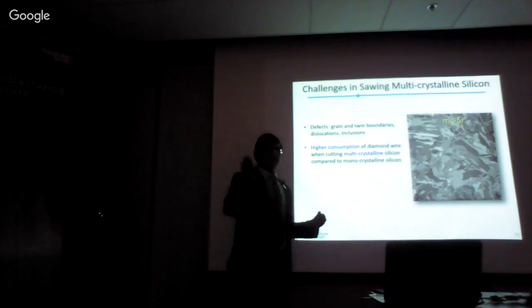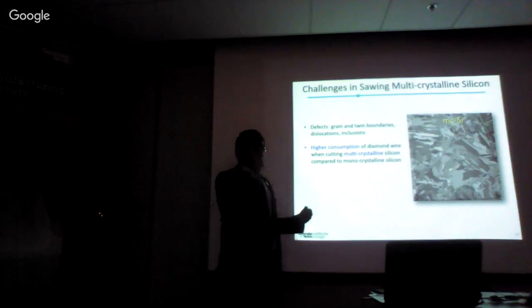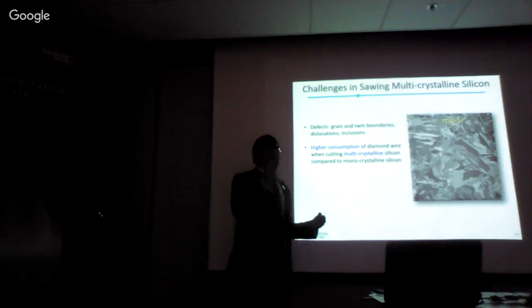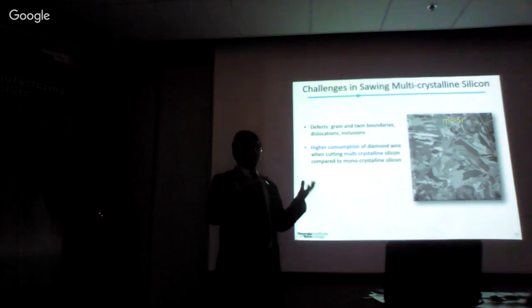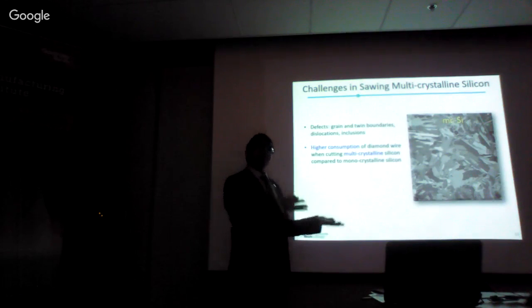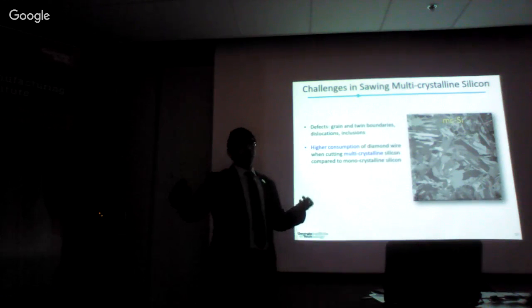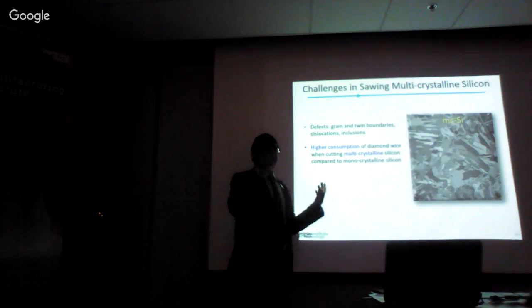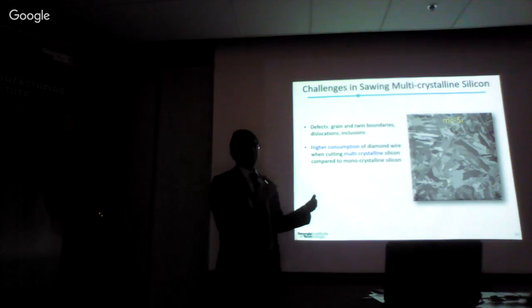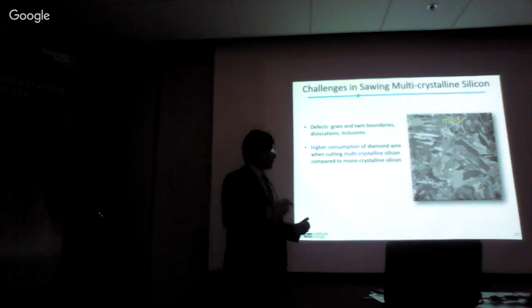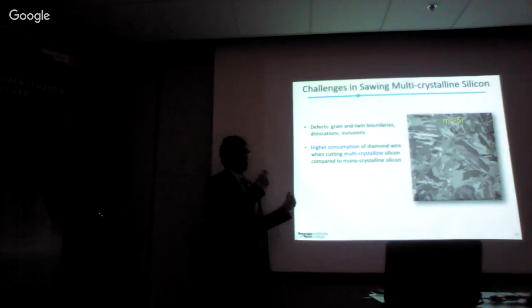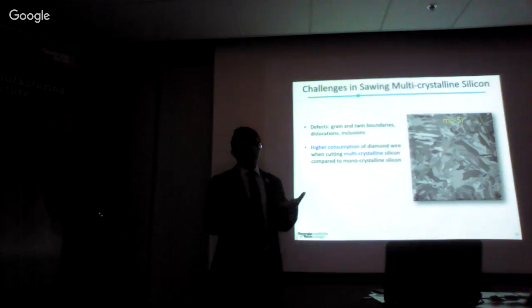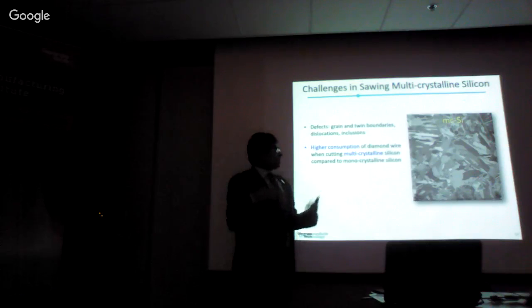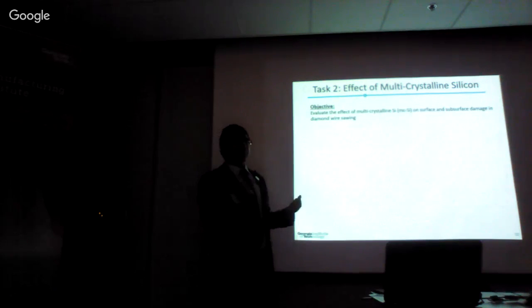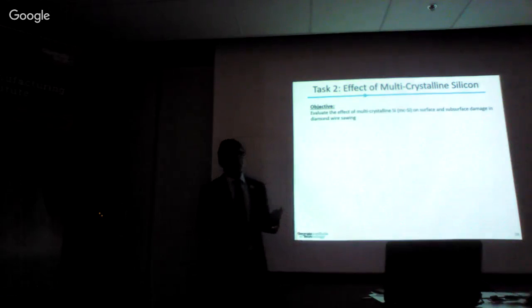boundaries, apart from silicon carbide, nitride inclusions, and dislocations, which affect the cutting of multicrystalline silicon wafers, leading to lower fracture strength of these wafers compared to monocrystalline silicon, and that leads to lower manufacturing yield. More wafers break when we are cutting multicrystalline silicon compared to cutting monocrystalline silicon. And the second challenge is greater consumption of the expensive diamond wire when cutting multicrystalline silicon compared to cutting monocrystalline silicon.